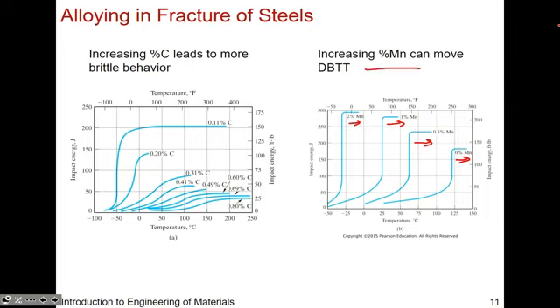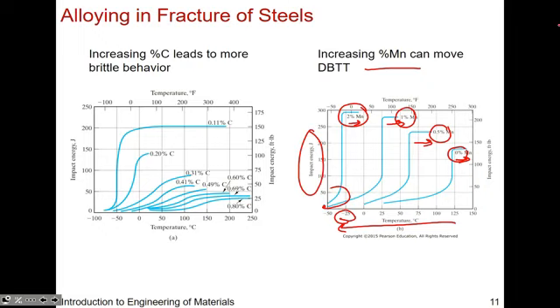So you can add in, let's say, substitutional components. Here it's a particular steel, so if you add in some substitutional manganese, you can actually decrease, as you can see here, from 0 to 0.5% to 1% to 2% manganese, the ductile to brittle transition temperature. So now your material is safe to operate at, I would say, negative 25 C and above. Now, safe is a highly nuanced term. If I'm just looking at this transition, then this is the predictor, right? Is it above or below this ductile brittle transition? Above, it's going to be ductile. Below, it's going to be brittle, okay? And you can see that here. The impact energy is quite low below this transition temperature, where it's quite high above, right? It can absorb a lot of energy above this transition. So it can plastically deform and give you some sort of warning, okay, before rupture.